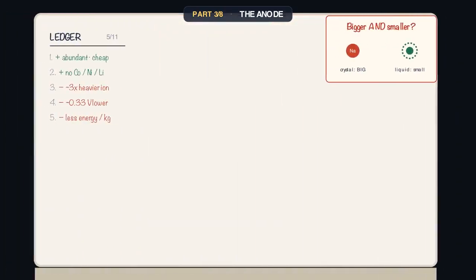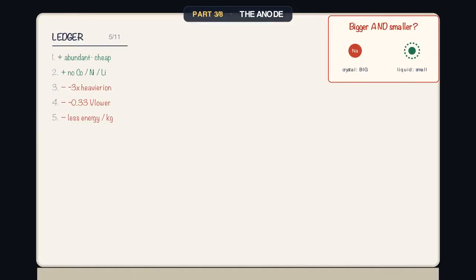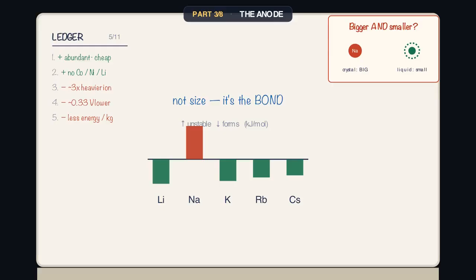And here's the trap almost everyone falls into. They say sodium is simply too big to fit. It's wrong. Potassium is even bigger than sodium, and potassium slides into graphite just fine. So size is not the culprit. The real reason is bonding. The sodium-carbon bond is just too weak to pay for cramming in, so the whole compound is unstable. It's subtle chemistry, not geometry, which means we can't fix it by squeezing harder. We need a different carbon.